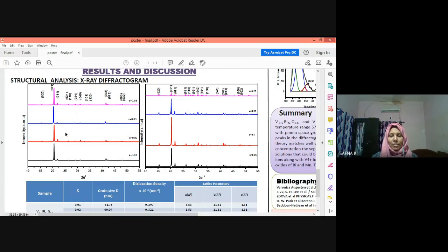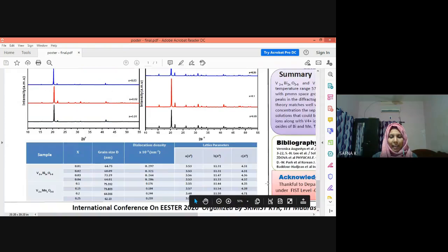All samples show the same phase and structure as that of pure V2O5, which can be indexed with orthorhombic structure in the Pmmn space group. And the obtained data shows insignificant variations in lattice parameters, suggesting successful insertion of manganese and bismuth ions in the V2O5 matrix lattice.